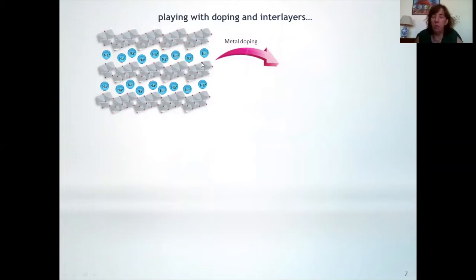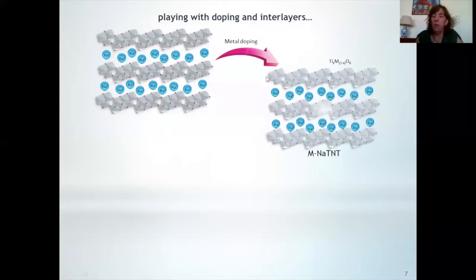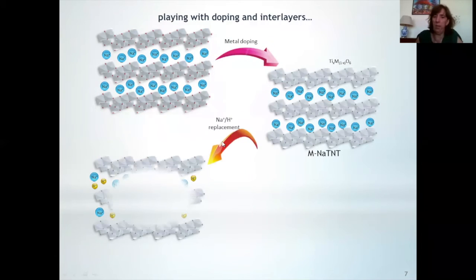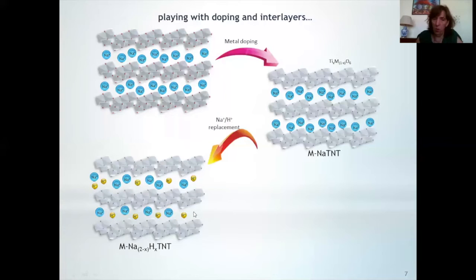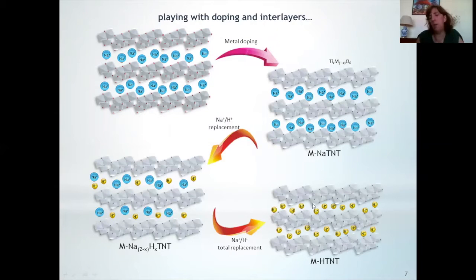So, but we can also try to think in doping these structures. Why? We just need to prepare an amorphous precursor. And we will be able, after hydrothermal treatment, to replace some of the titanium by the metal. As you can see here, the change of the octahedra changed, okay, to tell us that we have a doped structure. But nothing happens until now with this sodium. So why not try to replace the sodium? In the limit, once again, we can have a doped structure, with the H+ in the interlayers.